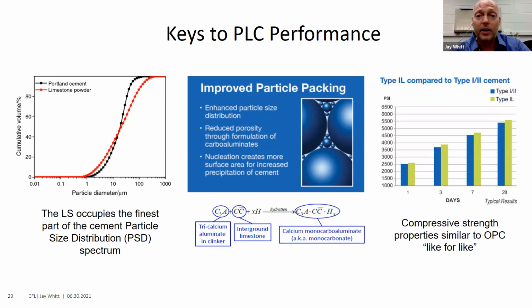What does it look like strength-wise? Most people, when they refer to strength, mean compressive strength. Well, we got very similar results, and we use the term like for like. It's not just adequate compressive strength, but also flexural strengths and all the durability testing, as far as shrinkage, ASR, and sulfate resistance. We are seeing like-for-like performance.